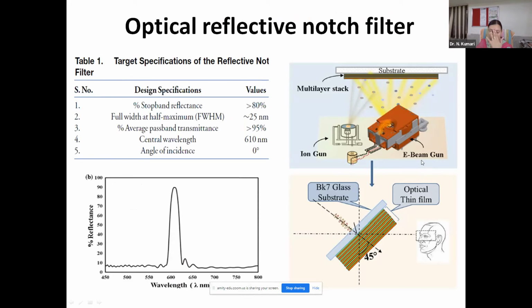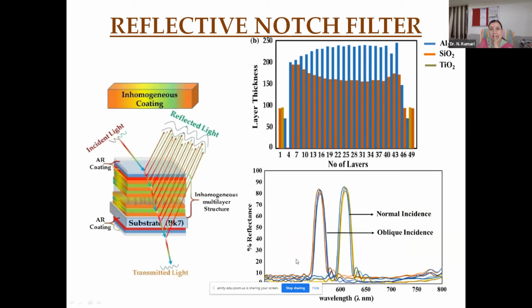But then we went for modulated thickness design, where we can design the refractive index in such a way that we can find out that the reflection is maximum along with the lower side lobes. This design was also further modified, and we could see that we can have a design in such a way that the conventional design is not gained, and also some anti-reflection layers are used at the end and the beginning, so that the index matching can be done with the atmosphere or with the air in this case. So using that one, we are able to reduce the outside reflection to a quite low value, and also we are able to gain the highest reflection at the desired window.